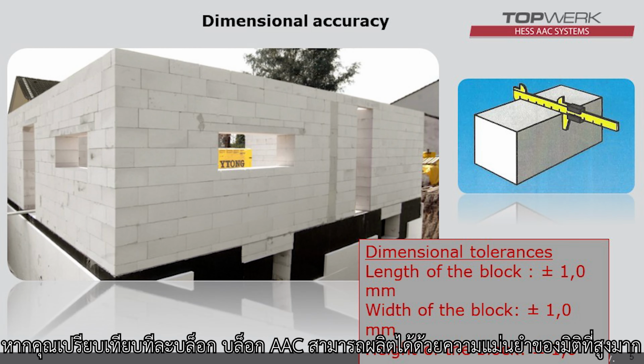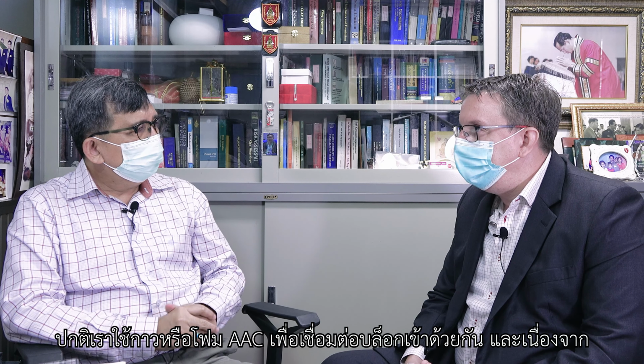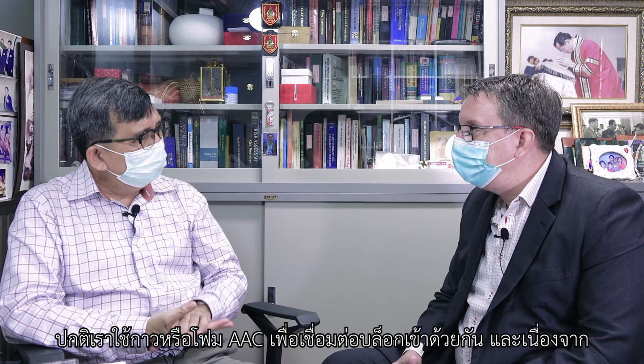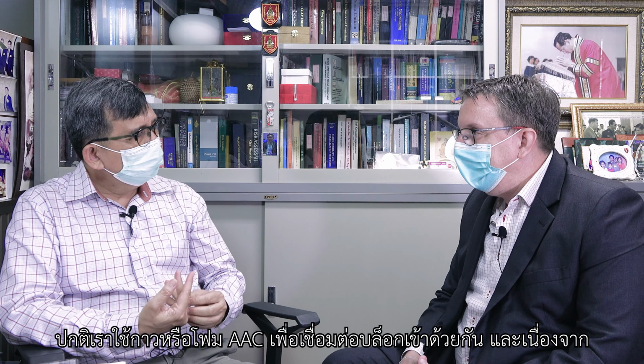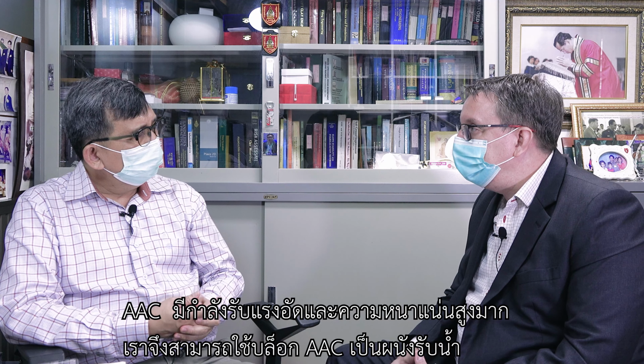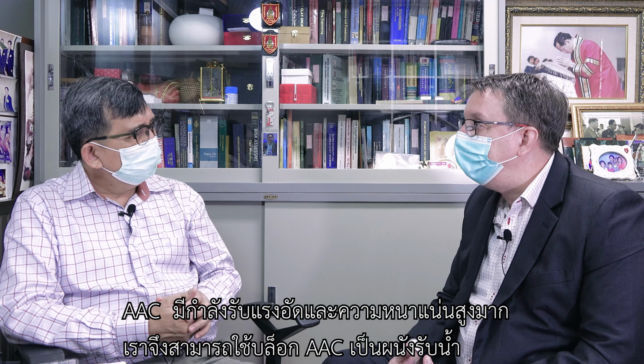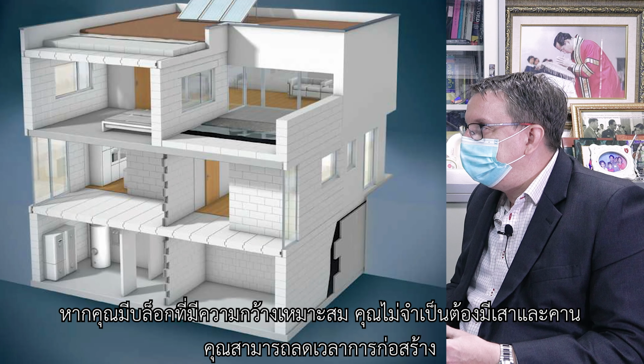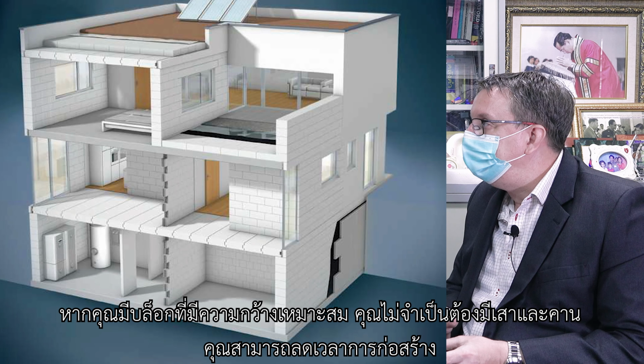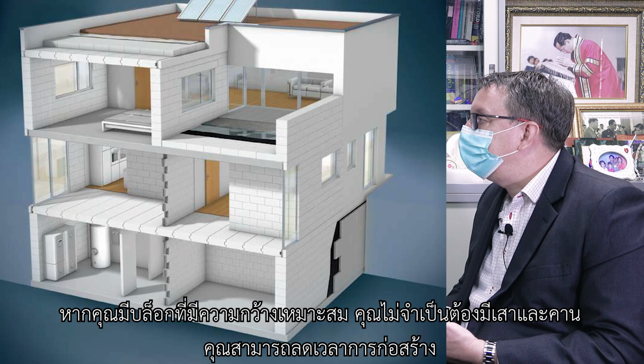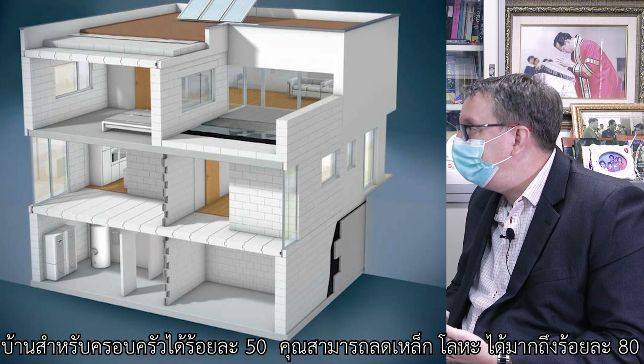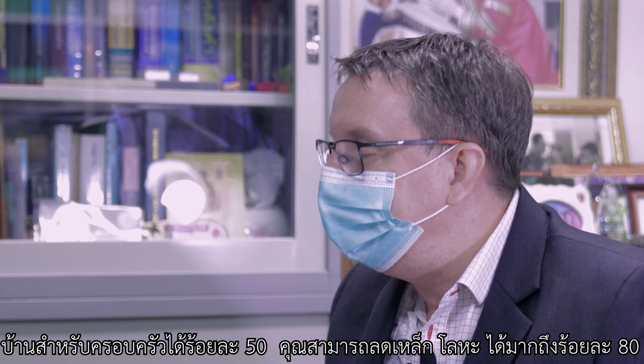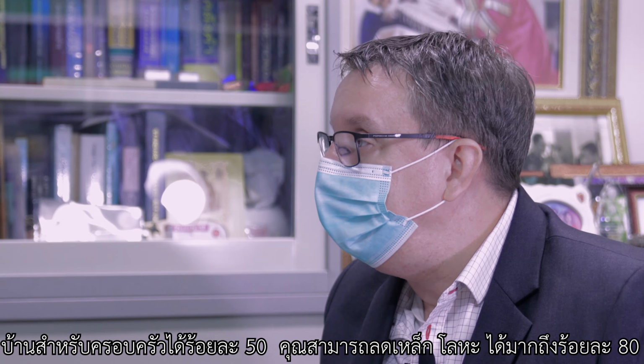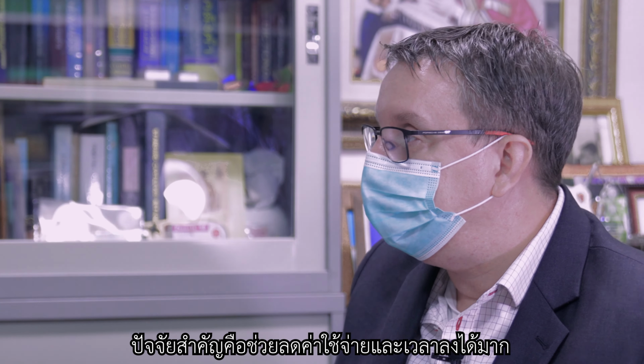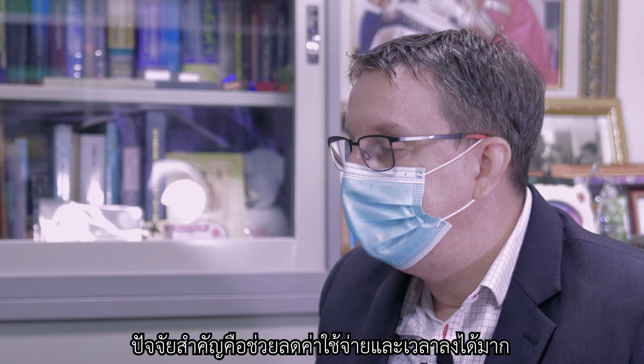If you compare block by block, AAC blocks can be manufactured with a very high dimensional accuracy. We normally use AAC glue or foam to connect the blocks to each other. And because of its high compressive strength and density, we can use AAC blocks as a load-bearing wall. So if you have the right width for the blocks, you don't need columns and beams. You can reduce construction time of, let's say, a family house by 50%. You can reduce steel by up to 80%, which reduces a lot of cost and time.